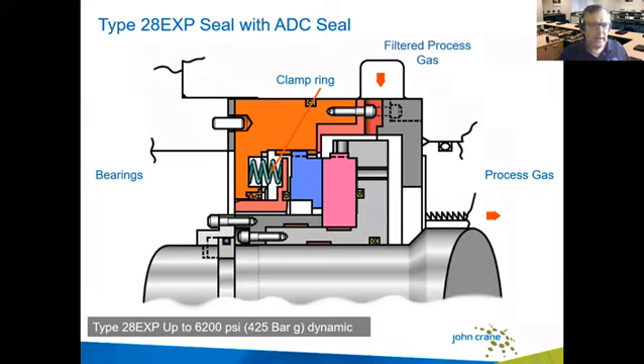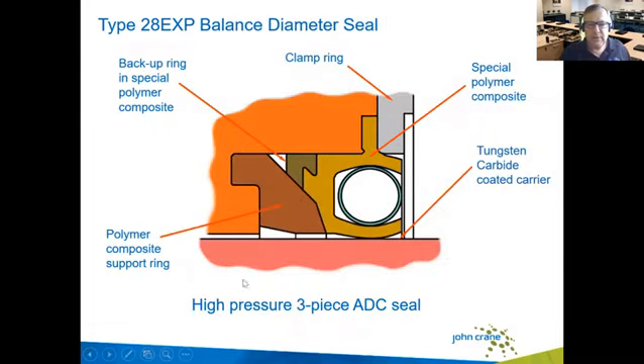And if we look more clearly at this ADC, we can see how it's actually constructed. It can be made of 2 pieces or 3 pieces. On the screen, we have a 3-piece ADC made up of the polymer, which is in contact with a coated surface of tungsten carbide. There is the spring. There is a backup ring made from a special polymer composite, and also another polymer composite used as a support ring. Note there's a small gap here. Once the seal is under pressure, this support ring will distort. It will come down and close up this gap, thereby preventing any extrusion. This backup ring is also to prevent extrusion in this direction.